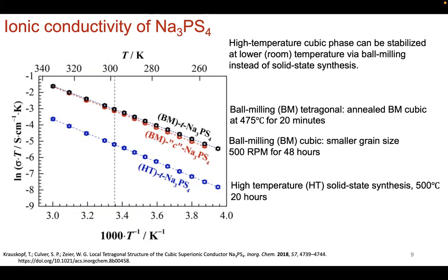Now, you can also ball mill the tetragonal phase, and you can also get the tetragonal phase by just annealing the ball mill cubic phase at some gentle temperature, like 475 C. Now, if you're working in solution phase synthesis, 475 C is actually quite high, but in the solid state regime, that's quite low, and you're probably just tickling the material a little bit. It's 475 C for 20 minutes, which is a very short anneal time. In conventional solid state synthesis, you could be annealing for 24 hours, 48 hours, multiple days, even multiple weeks. So you can control the crystal structure that you get at the end of the day by just changing up your synthesis method.